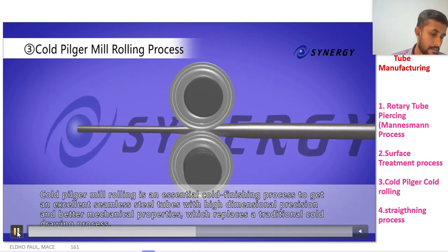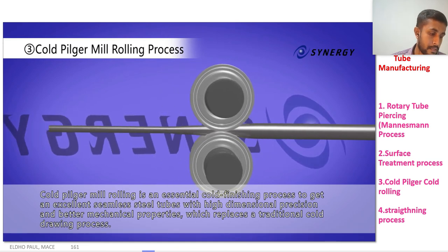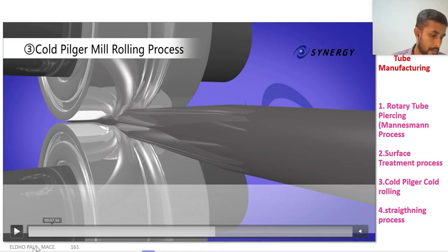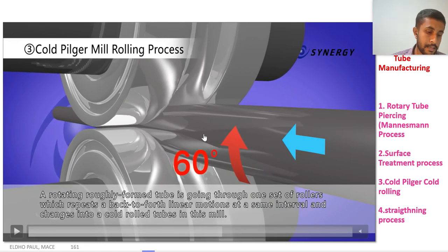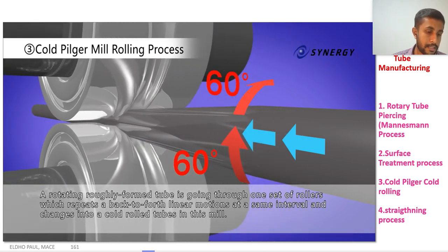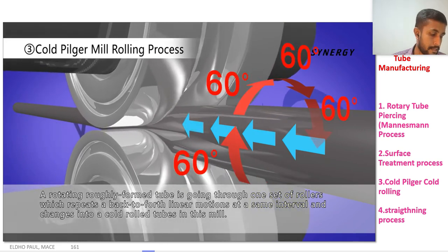Okay, actually the rollers are reciprocating, and this workpiece is moving forward while at the same time rotating. See, this workpiece is moving forward progressively, and at the same time it is rotating periodically during the process. Here in this, it is rotating by 60 degrees.